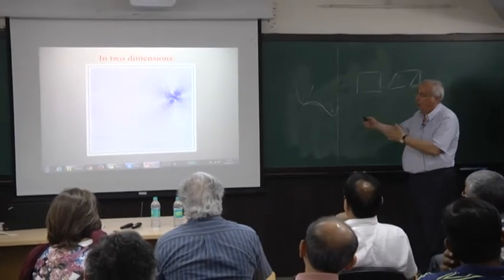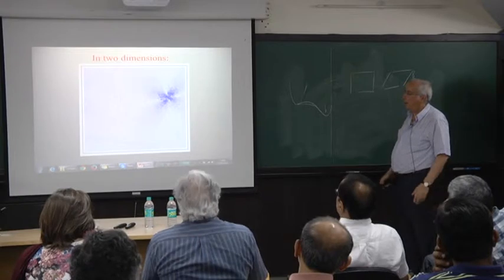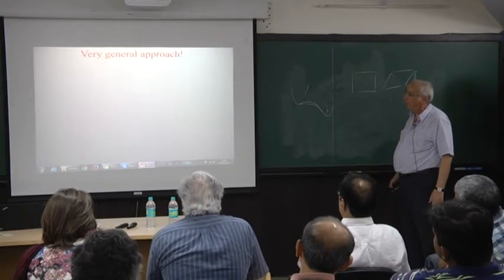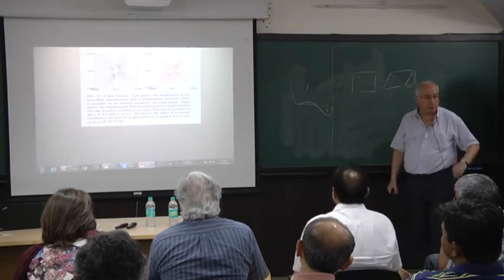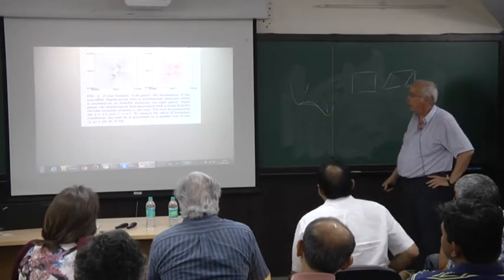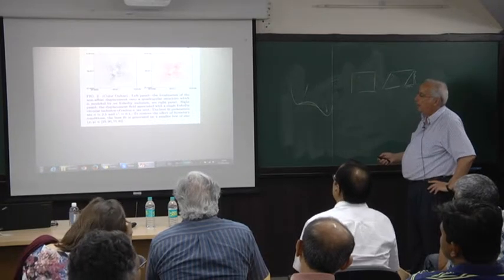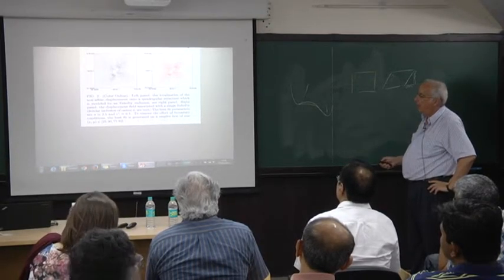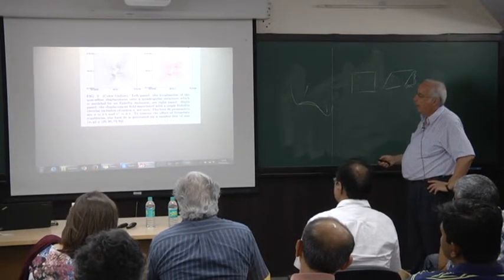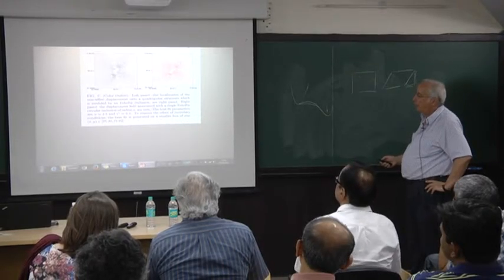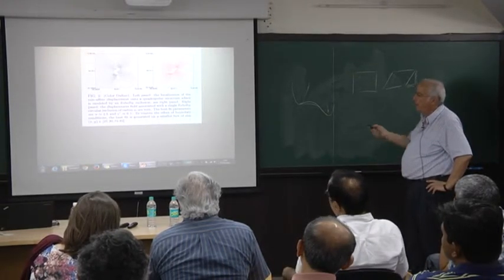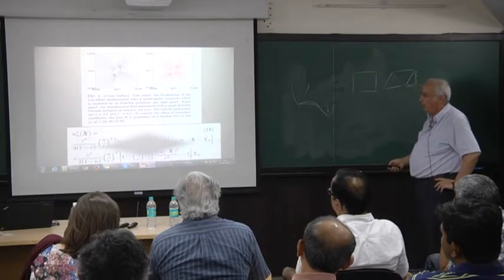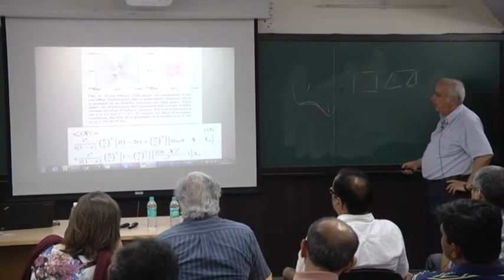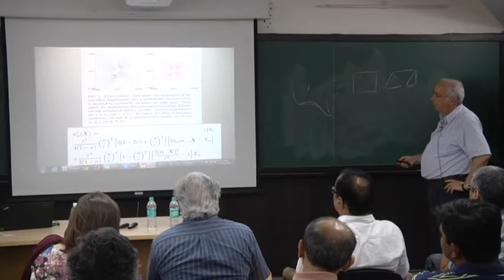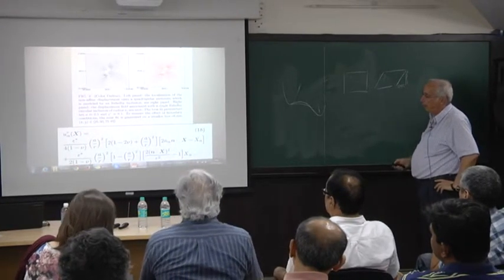And this is why these two problems are actually falling on each other. So here you see a plot that Tratul has actually produced when he was with us, of a spontaneous non-affine movement of the particles versus an Eshelby's solution. And this is an analytic solution in the sense that I can write the displacement field as a function of distance from a core. So this x as a vector.